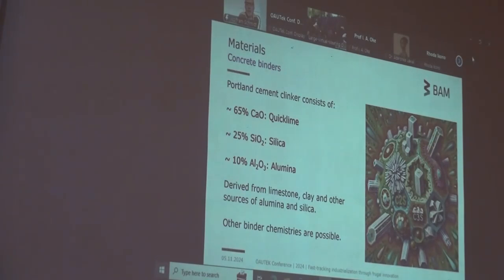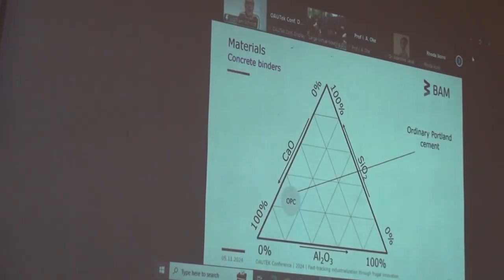So we have an established cement chemistry, which is the ordinary Portland cement, and we can put it into such a ternary diagram where on the left side you can see from 0 to 100% calcium oxide. On the bottom you can see the alumina, and on the right side you can see the silica, and we have about these 65% calcium oxide. We've got actually something like 10% alumina, and we've got 25% silica. That is the chemistry where we are looking at.